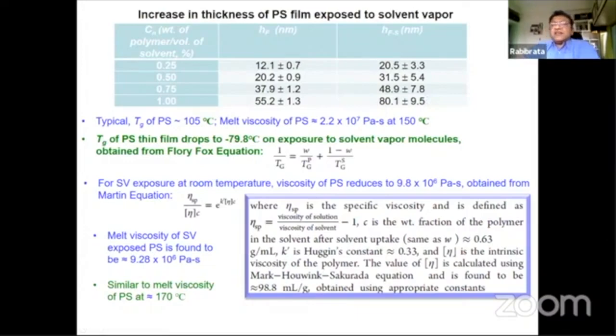Then we decided that let us calculate some numbers critically. Instead of always being qualitative, let's try to quantify what we are observing. So first thing we did was we calculated the glass transition temperature from what is known as the Flory-Fox equation. And that showed that upon solvent vapor, the glass transition temperature of polystyrene drops to -80°C instead of 110°C. So yes, the conjecture people have that at room temperature you have a liquid-like film is indeed valid. Then we calculated from the Martin equation the melt viscosity of the solvent vapor exposed polymer, polystyrene. And this is the equation.